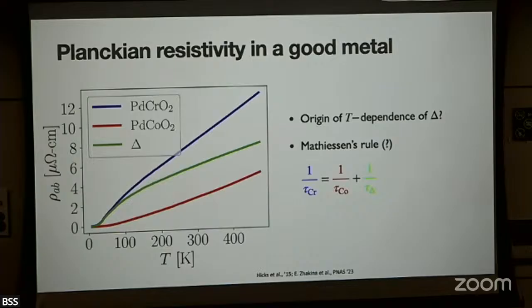Okay, so the question is, what is causing this excess scattering, and why do you get a T-linear resistivity in chromium oxide? Whenever I talk about this, I'll tell you a possible explanation, but I always like to hear if someone has any ideas. What are the suspects that might lead to this Planckian T-linear resistivity? Hotspots because of the Van Hove, but the Fermi surfaces of the two compounds look almost identical. So you have to invoke something that's building on top of cobalt oxide. Yeah. The nuclear spins of chromium, cobalt. And what would that do?